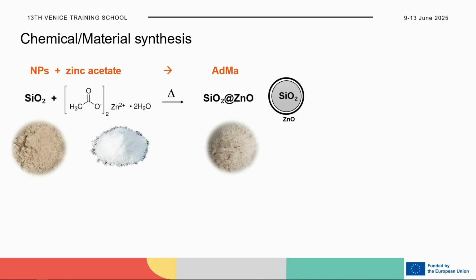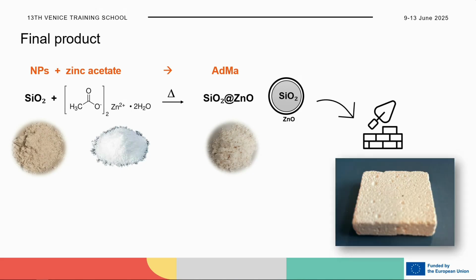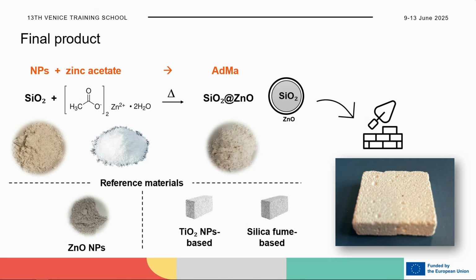So starting from the material characterization, material synthesis, what we have here is that the material started from the nanoparticles, silica nanoparticles that are commercially provided, and then they were mixed with a chemical, okay? So it's not nanomaterial in this case, it's a salt, it's a zinc acetate salt. Through some different steps in the lab, we obtain this silica dioxide and zinc oxide advanced material. Of course, then this was added to the final product to try to achieve the aim of converting nitrogen oxides in the air to nitrates.